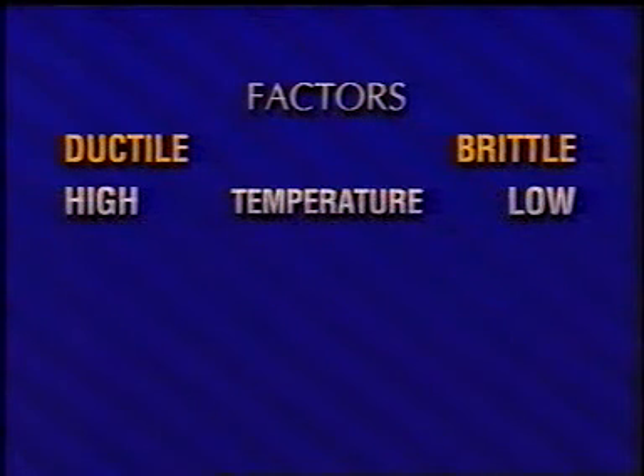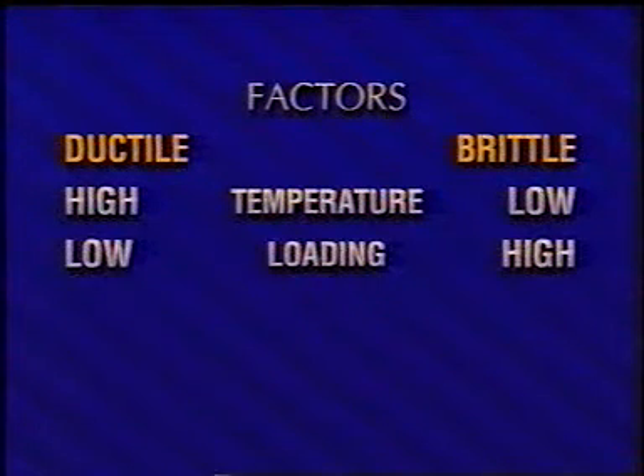Certain factors will affect the ductile-brittle relationship in metals. These factors indicate the trends most likely to affect the behavior, particularly in metals such as iron and steel, which have a cubic crystal lattice. Temperature. At high temperature, ductile behavior is more likely. At low temperature, brittle is more likely. When the rate of loading is low, ductile behavior is more likely. When high, brittle is more likely.